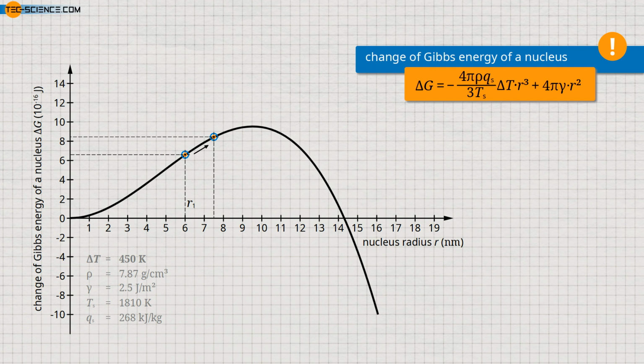Let us now consider a randomly formed nucleus with radius r2 located to the right of the maximum of the curve. This formation is also initially caused by thermal fluctuations in the melt, which lead to a corresponding increase in the Gibbs energy in the short term. In this case, a reduction of the nucleus radius is only possible by adding energy, which means by increasing the Gibbs energy, and will therefore not occur spontaneously. The nucleus does not disintegrate. Rather, the solidified nucleus will spontaneously increase its radius by decreasing the Gibbs energy. Of course, this can only happen if more molecules from the melt attach themselves to the nucleus. This is the beginning of nucleus growth and the solidification process begins.